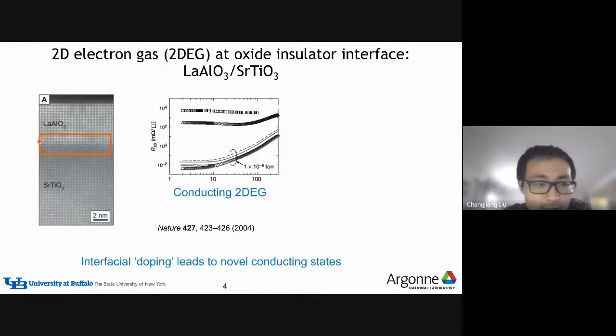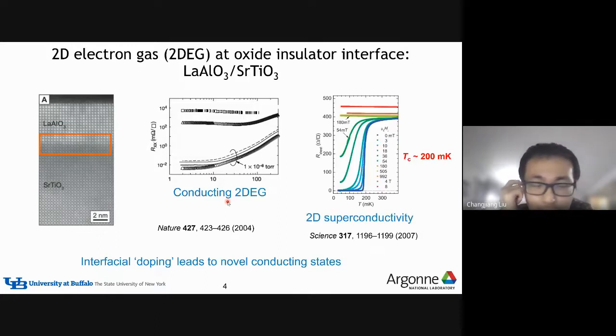It turns out that at this interface, additional charge carriers are generated just due to the special electronic structure or interfacial doping effect. And these charge carriers are confined just within the interface region, a very small region. So basically, they become a two-dimensional electron gas. Later on, people found that this metallic electron gas can even become superconducting, meaning the resistance can go to zero at a sufficiently low temperature. For this system, lanthanum aluminum oxide on strontium titanium oxide, or LAO/STO, the superconducting transition temperature is around 200 milliKelvin, so quite a low temperature. But still, this system is very interesting.